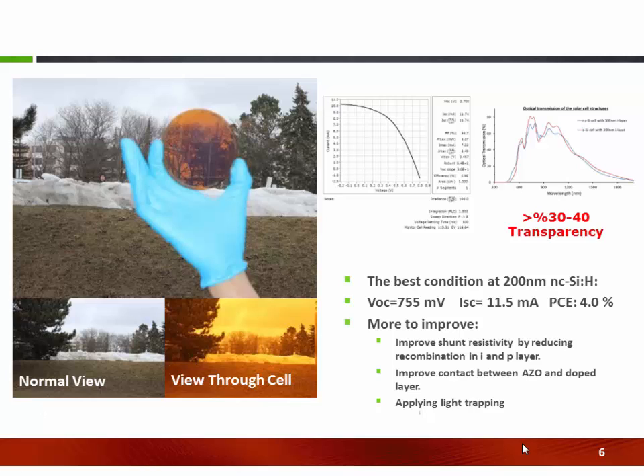The final achievement was a device with an efficiency of around 4%, around 750 millivolts, and a short circuit current of around 11.5 milliamps. But there is a lot of room for improvement in these devices because the fill factor is the main limitation for us. We are now at a 45% fill factor, but we're looking to improve it. This performance is promising because we didn't use a metallic contact and we didn't use ITO, but just AZO at the top and back contact.